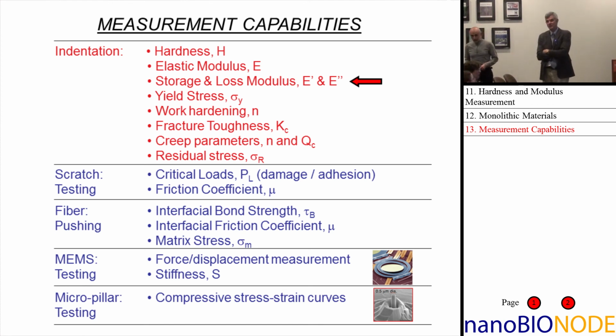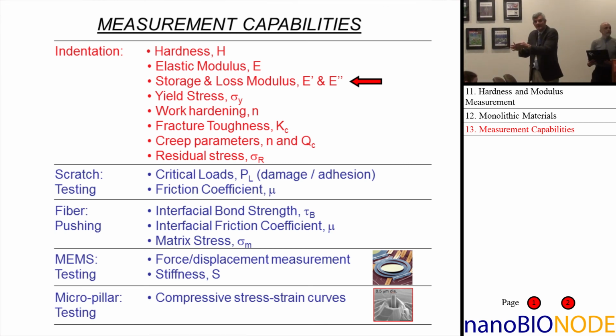Yeah, so that's a very good point. All the data that I showed you this morning is done nominally with a sharp Berkovich tip. And tips, even Berkovich tips, you use them a few times, they start getting dull, and the tip geometry starts to change. When the tip starts to get rounded, the contact mechanics at small depths change from perfectly sharp elastic-plastic contact towards the contact mechanics of spherical indentation, which starts off with finite stresses and elastic deformation only. So if you've got a dulled tip, and this is something a lot of folks don't appreciate, there is a change in the basic contact mechanics as you go from large depth to small depths that, if you don't account for it properly, will have the appearance of making it look like the material properties are changing. Is that answering the question you're asking?